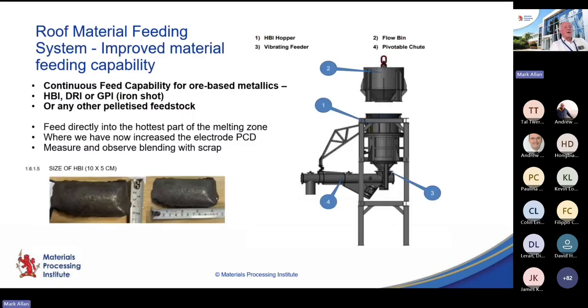The next key factor I want to talk about is the facility for us to continuously add material through the furnace roof during operations via the hopper and vibration feeding system that you can see depicted here. In terms of supporting the transition from traditional blast furnace steel making into electric arc furnace steel making, there are, as many of the people tuned into this webinar will know, certain steel grades where, because of requirement for low residual element levels or low nitrogen levels, will require a proportion of virgin iron units to be blended in with the scrap-based mix, and this gives us the opportunity to do that.